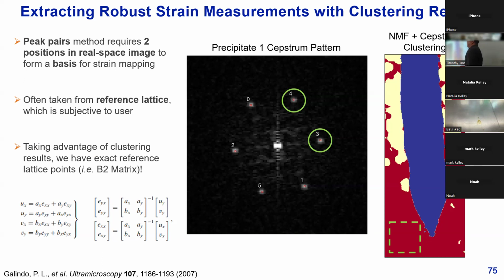So what we actually do is, in this Cepstrum pattern, we can measure the spot positions for every single pattern corresponding to cluster 0, which is the matrix. All of these patterns, even from up here or here, are going to be used to form a reference lattice by averaging all of those measured lattice parameters from these spots. And then using a set of fairly simple matrix equations here, we can obtain our strain using something called the peak pairs method in this case.